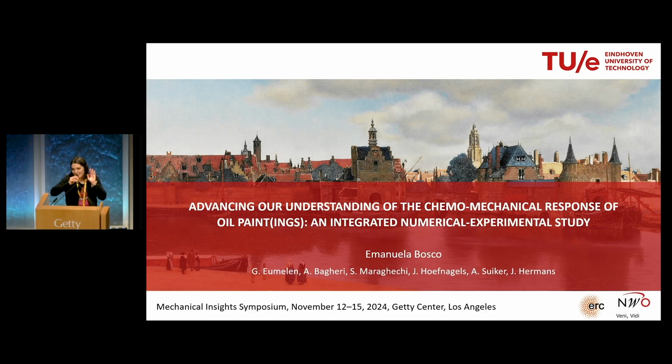I did not hear super well, but I think you asked me about the interaction with the chemistry, if I'm sure that there is no interaction with the chemistry in the experiments, right? About the speckle pattern. So the titanium white samples. One of the reasons why we chose it is because it's a pigment that is non-reactive, so it actually eliminates all these additional features. If we would test lead white, then of course that can also create metal soaps, ion migration, and so then it would be much more complex.